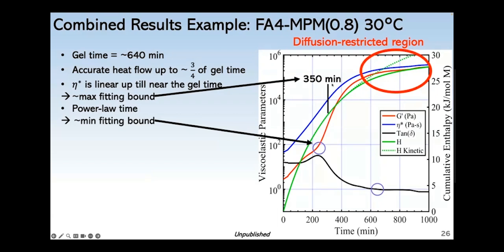And then I also noticed, so to give you some idea about how I picked the fitting bounds on that fitting equation, I noticed that the complex viscosity remained linear up to a certain point. And so I took that as the max fitting time. And then I chose my minimum fitting bound as the intersection point where the G prime suddenly changes slopes, which is this purple circle here.